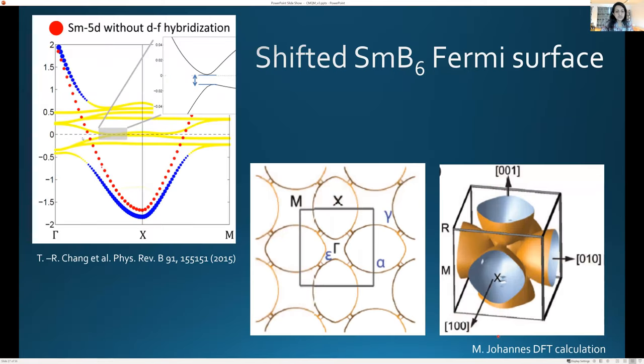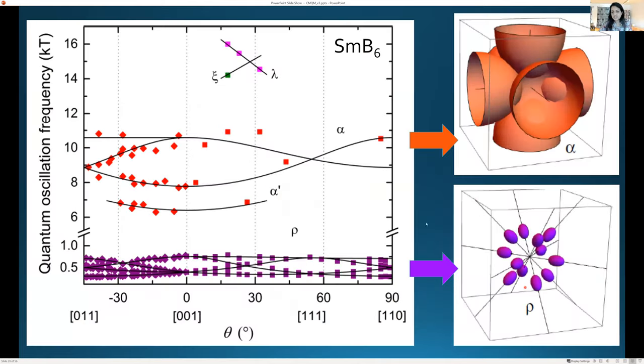As I briefly mentioned earlier, hybridization between the conduction and F electron bands of the samarium hexaboride gives you a gap. So what our collaborators Michelle and Johannes have done to try and simulate a Fermi surface in the samarium hexaboride is to manually lift the Fermi energy, so make the Fermi energy cross the band. She's had to shift it by a few electron volts. And in that case, yes, one does have crossing of the band by the Fermi energy, and she can simulate bands by forcing the Fermi energy to cross the band structure. But basically that's just giving you back the conduction electron Fermi surface.